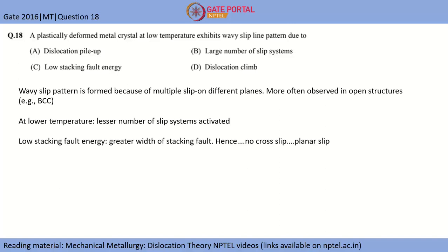And low stacking fault energy means greater width of the stacking fault. If the width of the stacking fault is greater, then cross slip of screw dislocations will be difficult.